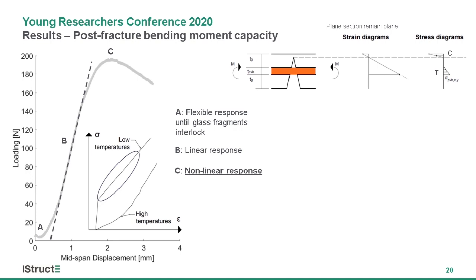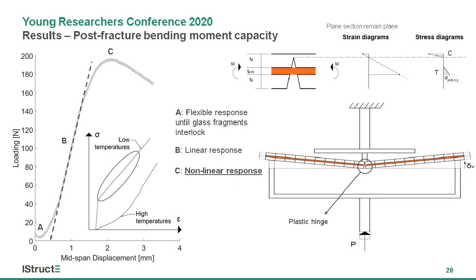A non-linear response is observed in the next stage due to the change in slope in the PVB material model. Although the transition point is often referred to as yield stress, it only refers to the stress at which a significant change in modulus is observed, rather than the onset of true plasticity. A plastic hinge eventually forms when the top glass layer crushes in compression, resulting in a collapse mechanism for the simply supported specimens tested. The moment capacity for this stage is derived by taking moment equilibrium about the plastic neutral axis.